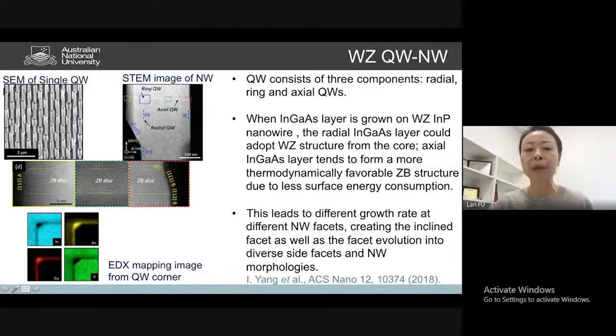We can confirm that by doing compositional analysis using EDX mapping inside TEM. You can see the different compositions of the quantum wells, and that the quantum wells are quite non-uniform in terms of composition, and we also have quite different components. We have this axial component, we have the radial component, we have a corner component reflecting over here. Of course, you can do the structure analysis. What we found is that our wurtzite-based indium phosphide, after growth, has an actually complex structure. However, the main message here is that the quantum well, which is here, is actually zinc blende based. So basically, when we grow indium gallium arsenide material, that layer becomes zinc blende, which is a cubic lattice. And wurtzite is a hexagonal lattice. So they're very different crystalline structures.